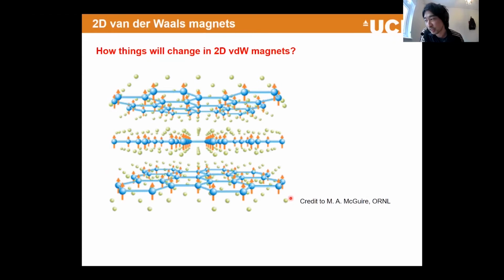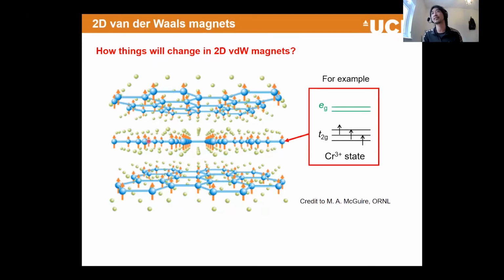I just want to introduce a new material group. It's just like graphene. Of course, this is the 2D materials session. They are just layered materials. What's different between the ones already discussed and this one is that it simply has a spin. That's because one of the elements inside these layers is, for example, chromium, a famous 3D transition metal used to create antiferromagnets. It has, for example, the chromium 3 plus state, and if you put 3 electrons inside this electronic structure and the crystal field is involved, then you can create 3 spin polarized states that we can exploit for magnetism and also spintronics. So that's the key thing, and we need nothing else than this ingredient for this application.